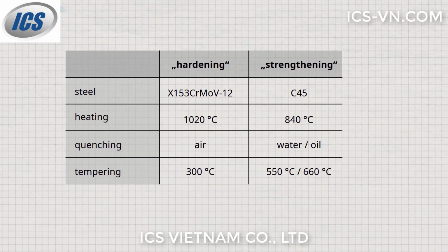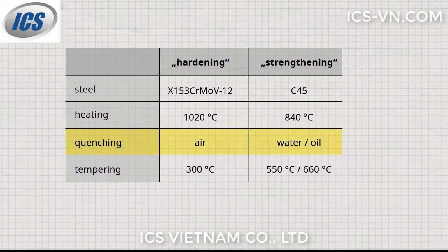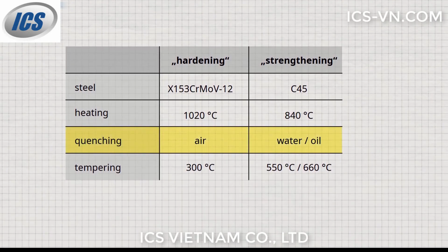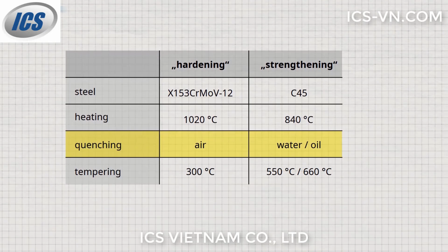The comparison of the two steels again clearly shows that unalloyed or low-alloyed steels have to be cooled in stronger quenching media than high-alloyed steels. On the other hand, it is again evident that the tempering temperatures are lower during hardening.